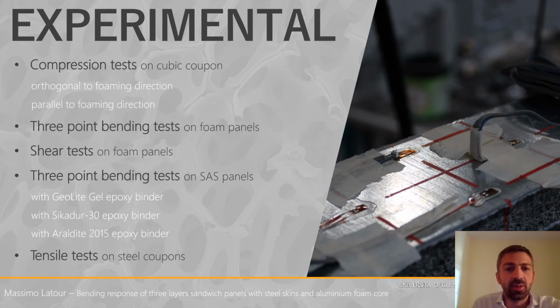The experimental tests we have executed in this work are extended to tests on the simple foam in compression and bending, as well as shear, and 3-point bending tests on steel-aluminum-steel panels, which were tested considering different types of epoxy binder. The compression tests were executed on the foam, referring to the transverse and parallel direction, meaning in this case transverse or parallel to the foaming direction. The type of glues that we've used have been produced by different companies. In particular, Kerakoll for what regards Geolite, Sikadur-30 is Sika, Araldite 2015 is produced by Huntsman.